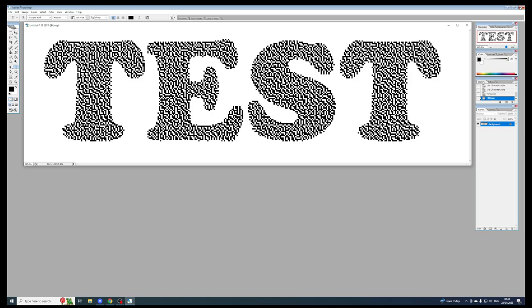Remember, I'm doing 800 millimeters a second. And at 254 ppi, that's 10 pixels per millimeter. 800 millimeters a second means I'm producing 8000 dots per second. So the beam is on nearly continuously, but it's not continuous. And that's the key factor about this process with stopping and starting the beam. Now, in reality, your eye can't see these dots, but it makes a huge difference to the amount of energy that you're putting into the surface. You're not keeping the beam on. You're not scraping away huge depths to the surface. You're producing little dot marks on the surface, which are not causing a huge amount of solid material to be converted into steam into vapor. And the vapor can just escape drift away without ever being blown or settling down onto your work. That's why I'm producing dust and not acrylic recondensation.